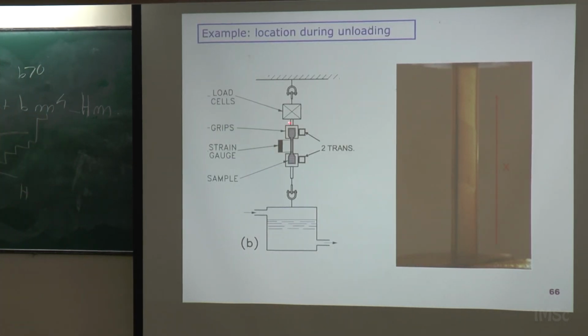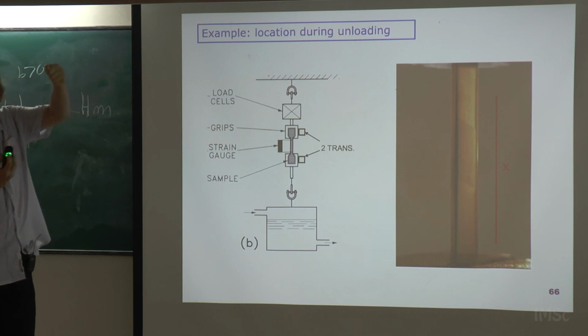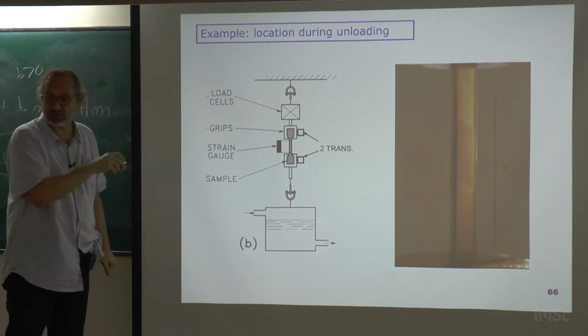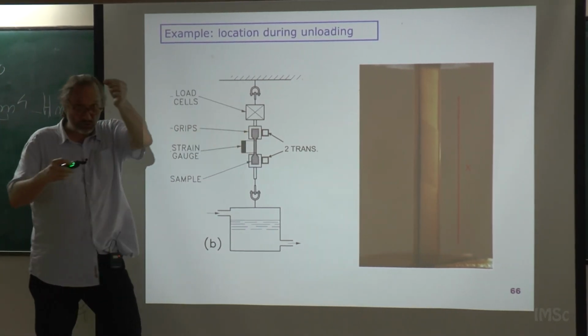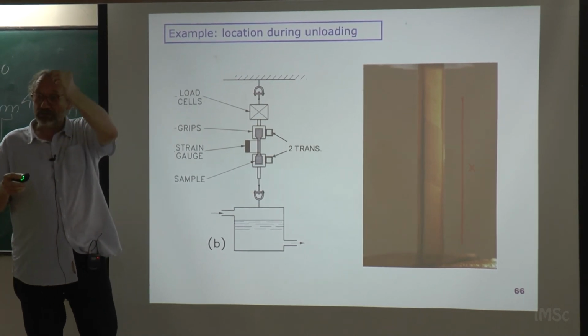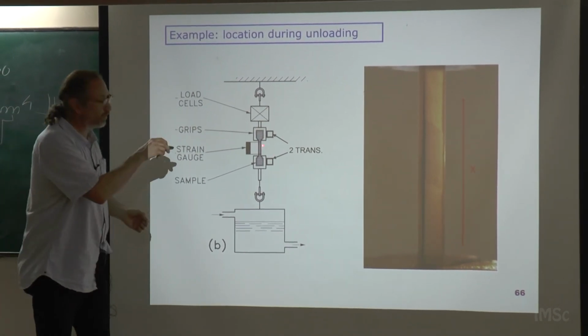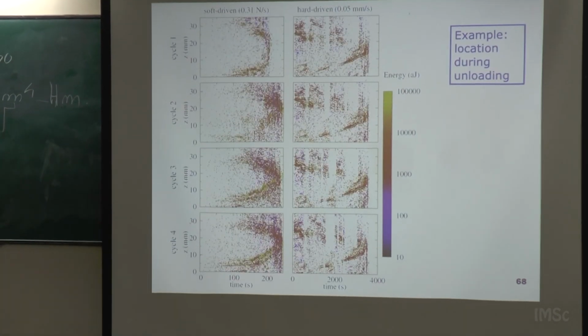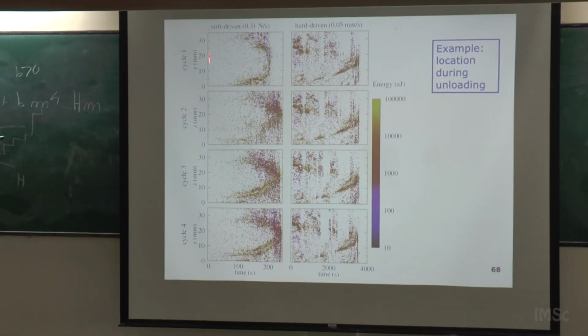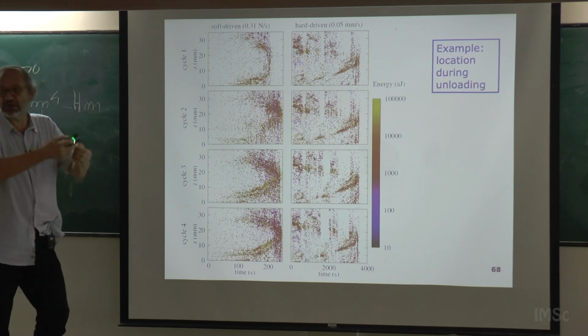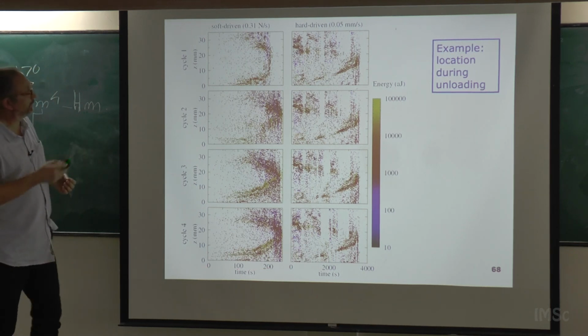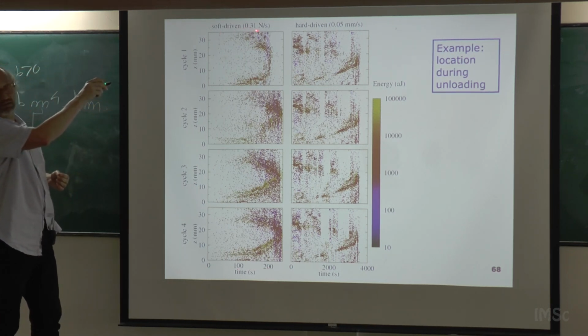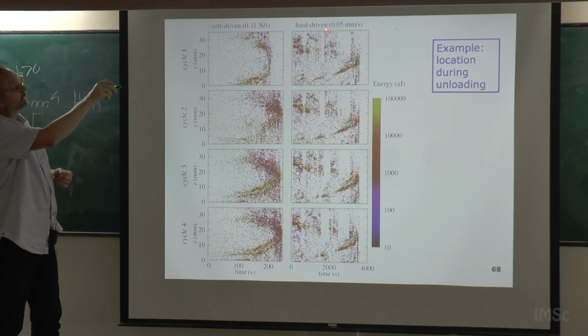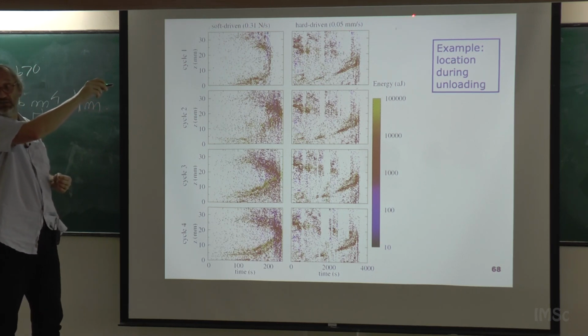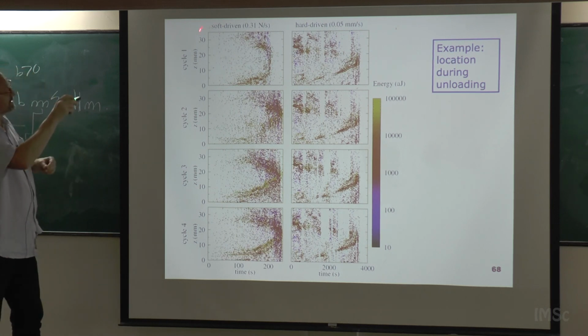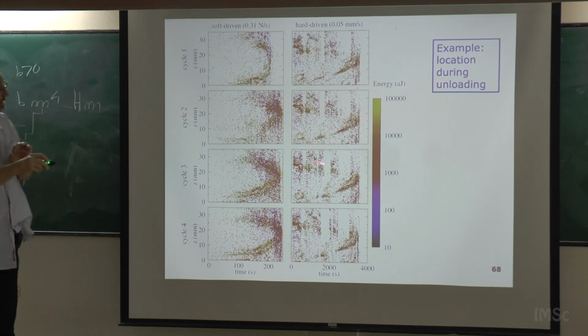Okay, so here in this case, when we do the experiment in the tensile machine, we put two transducers. And with two transducers, just looking at the time delay of the signals, you can know where the event was. Okay, and then you can see these things. This is time, where we are pulling. Here is soft-driven, meaning force proportional to time, and this means speed, constant speed. And we are pulling, this is Z, the position of the event, as a function of time.